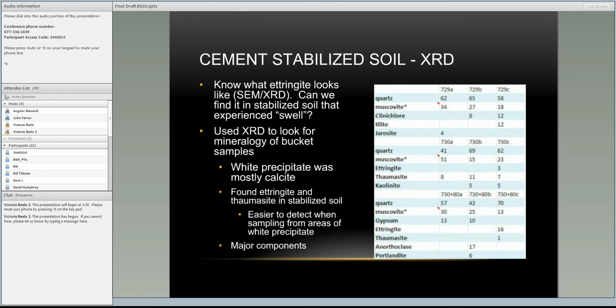And comparing the two spectrums, you can see that the main difference when going from a lot of soil with some ettringite to zooming in on the ettringite is that the silica content goes down, calcium goes up, and you'll get a sulfur peak where before there wasn't one. And then, of course, aluminum is important with ettringite, but you can also see that a lot of times in the soil.